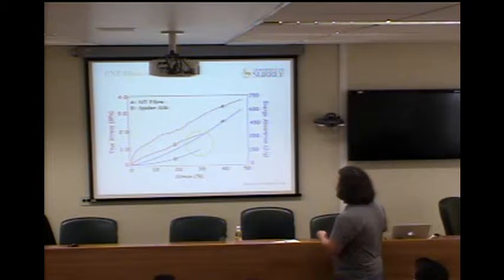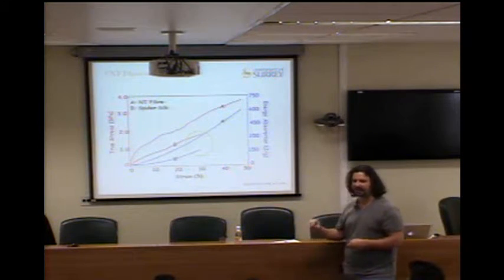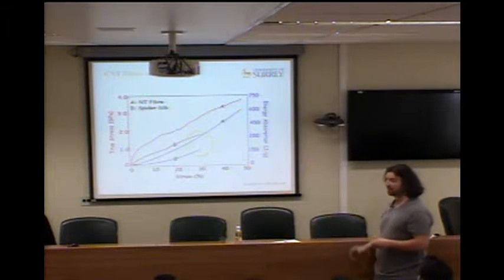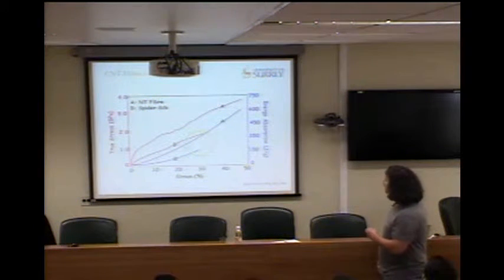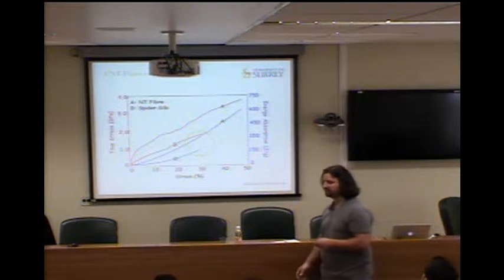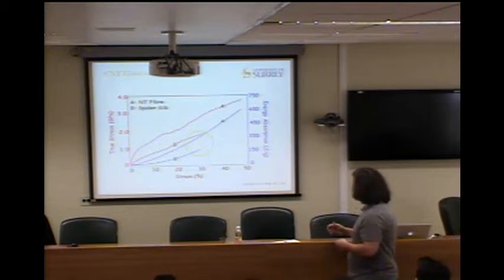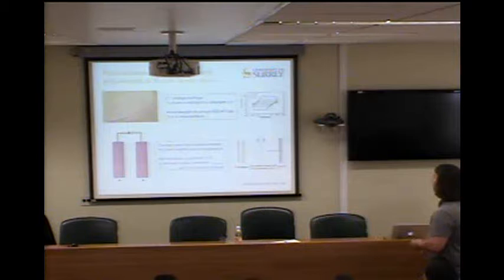But the really impressive number is if we look at this toughness or energy absorption. Spider silk, which was the toughest material in nature, has 150 joules per gram, which is a lot before it breaks. But these carbon nanotube fibers are 600 joules per gram, so a factor of 4 better than spider silk.